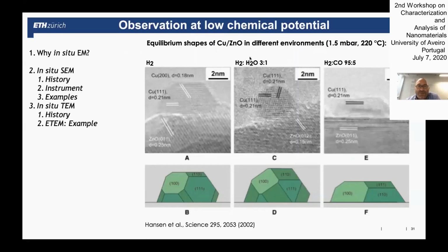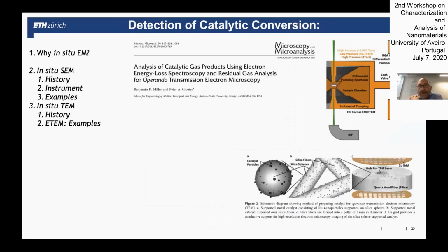And this is one of these pioneering works that was published in 2002 in Science, where they looked at a very important catalyst. It's a catalyst for methanol synthesis. It's usually copper and zinc oxide. And they studied how the different gas compositions change the properties of the particles in terms of shape, for example. So you could see different particles adapt to the chemical potential of the environment, and expose different facets and reconstruct to find a local energy minimum. There are different approaches. This is a nice paper I want to show you from Peter Crozier and his colleagues.